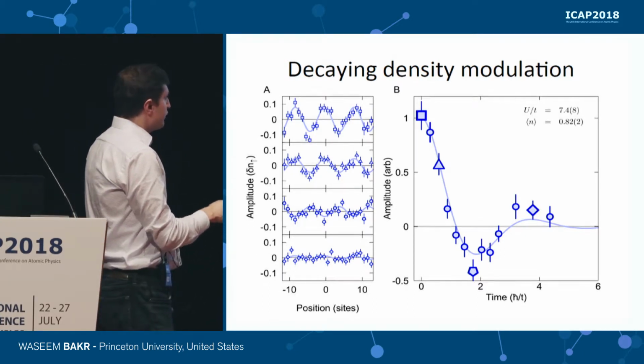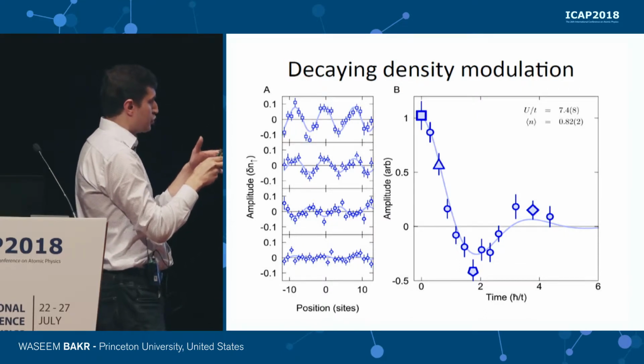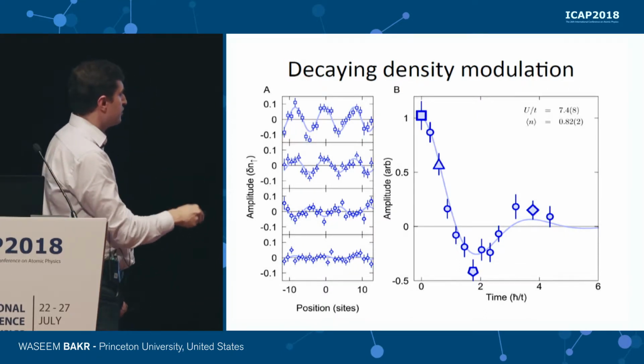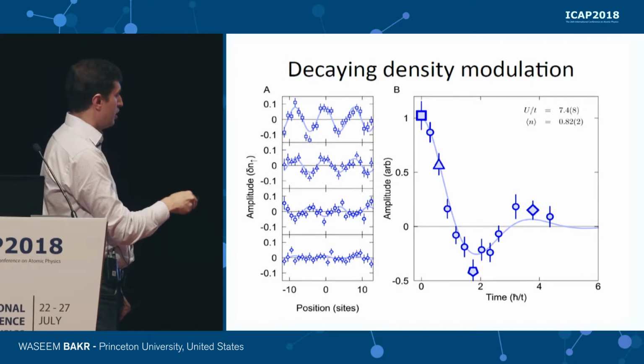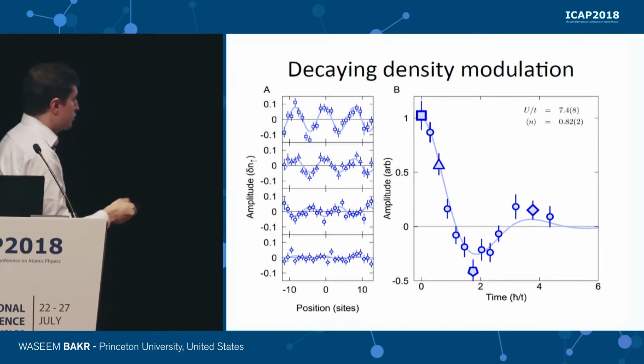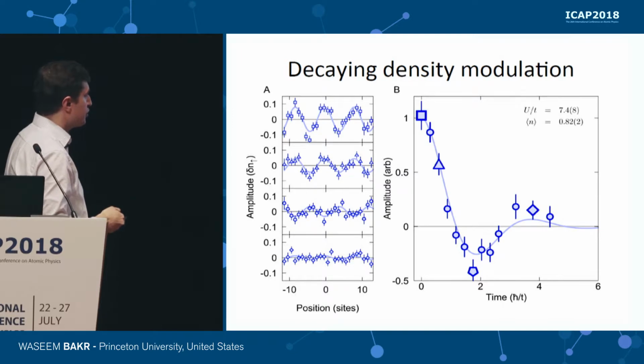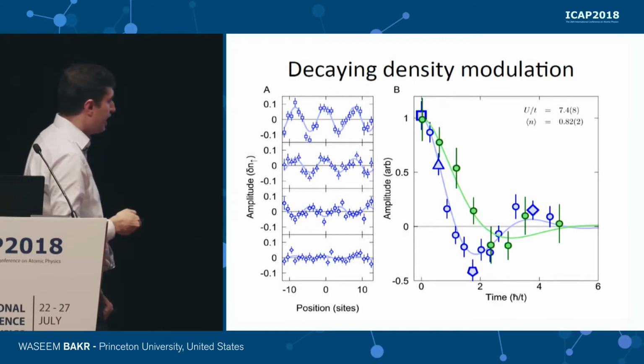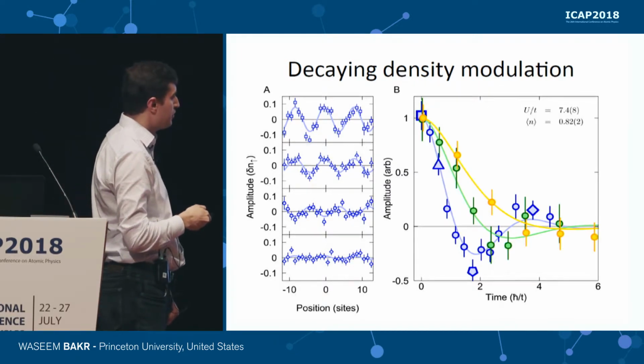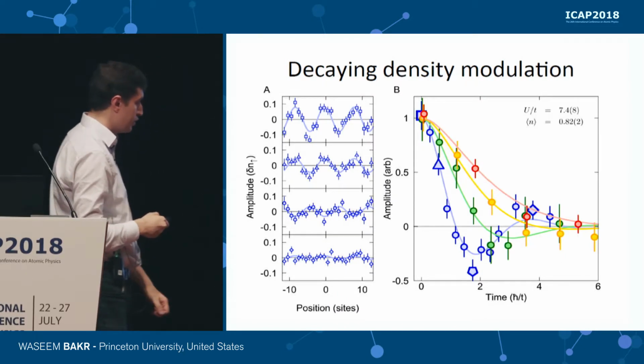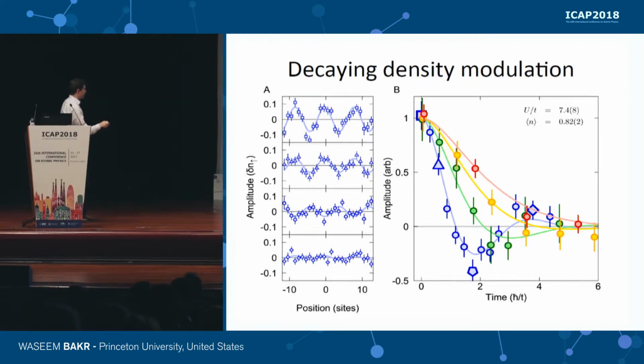OK, so this is for a modulation which is relatively short wavelength, 5 sites. And you can see that we see a bit of an oscillation, an under-damped oscillation. So this was for 5 sites. Now, for a modulation of 10 sites, it becomes a bit more damped. For 15 sites, even more damped, and completely overdamped at 20 sites. You could almost fit this to an exponential decay at that point.